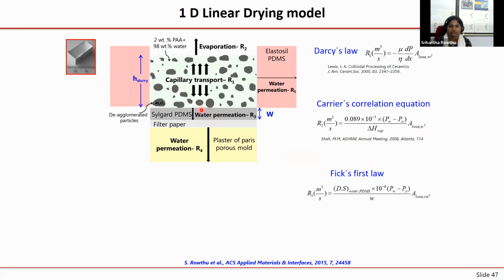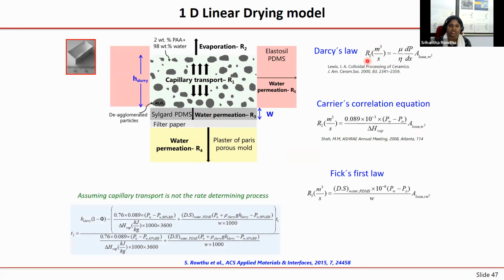Then for this water vapor permeation, one could use Fick's first law. By using this, we know how much liquid is present here. Okay. If I know the volume, and if I know the rates, they are nothing but volume per time. So one could actually say that my drying time for the whole slurry, that all the liquid has to be removed, comes up with this complicated equation. But don't worry, I'm going to show you what it is. So the first thing you have to see is my drying time is directly proportional to the slurry height. That is the first observation. Then the second thing is it is inversely proportional to the PDMS thickness. And the third thing is in all my rate equations, there is something called base area.